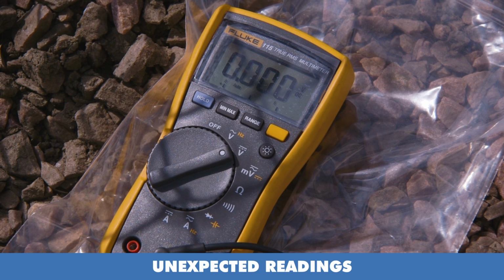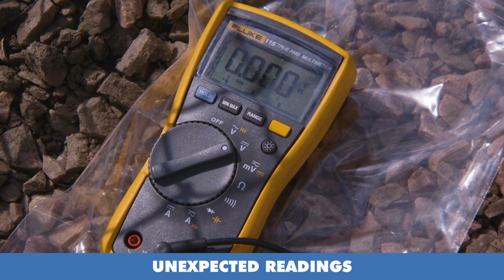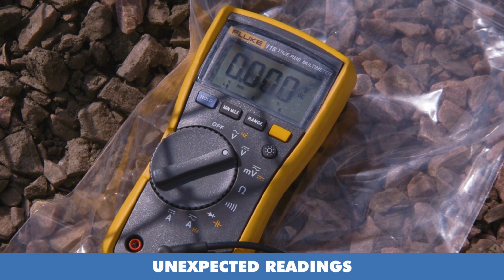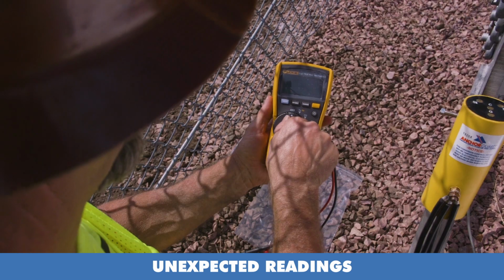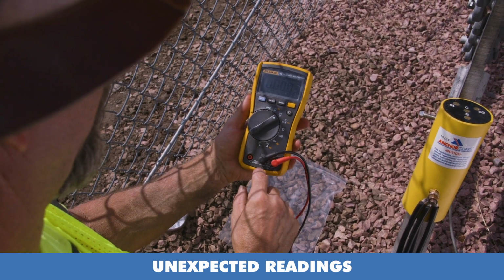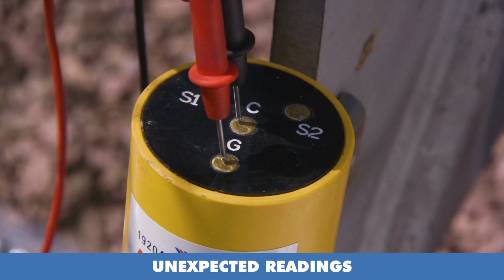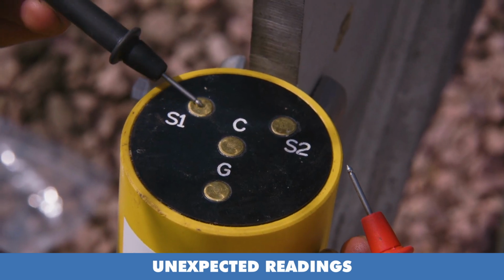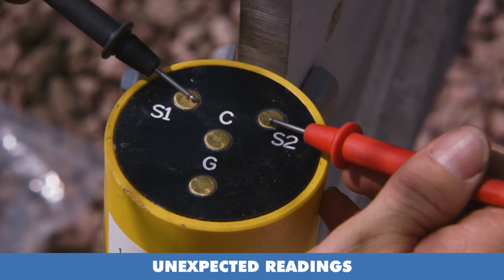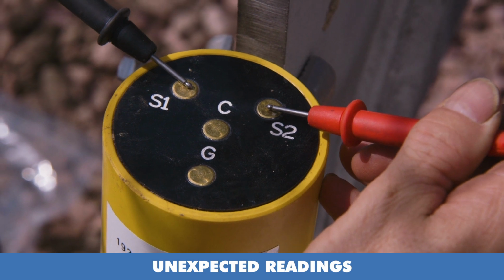Unexpected readings. If placing the voltmeter on the test points for the system performance test results in a 0 or close to 0 result, there are a few possibilities. The voltmeter leads are not making good contact with the test points. Clean the test points and check the function of the voltmeter, and make good contact with the leads.